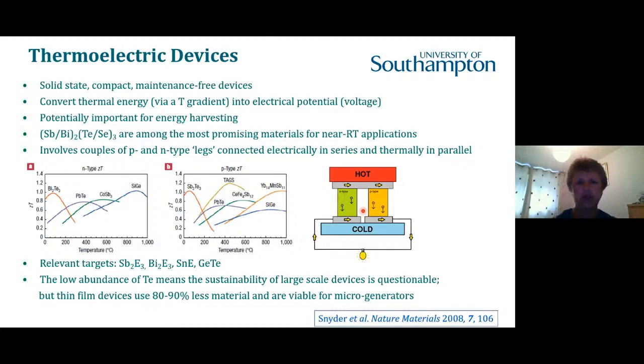In terms of the types of materials, there are quite a few different classes of thermoelectric material, but the antimony, bismuth, selenide, telluride family are amongst the most promising thermoelectric materials for applications near to room temperature, so from room temperature to maybe plus 100 degrees Celsius. And the key thing is that we need to have couples, little circuits derived from a combination of P-type semiconductor and N-type semiconductor legs.